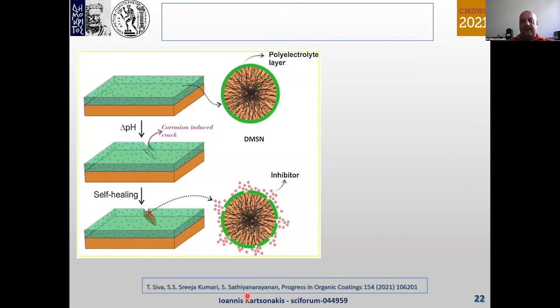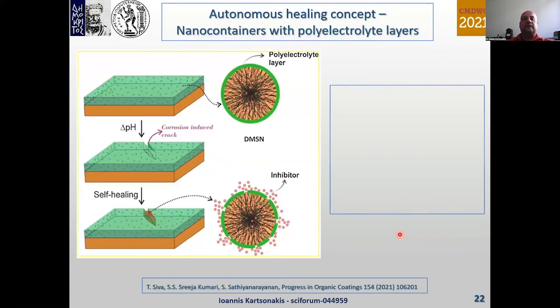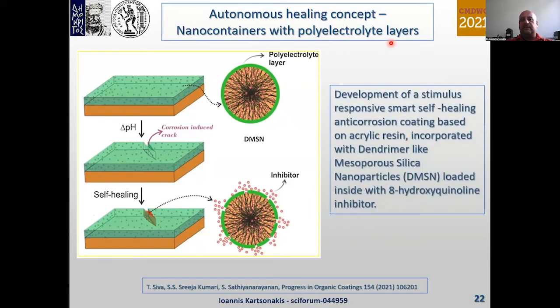In the work of Siva et al. in 2021, there was also autonomous self-healing, but this time with nanocontainers with polyelectrolyte layers. There was a development of stimuli-responsive smart self-healing anti-corrosion coatings based on an acrylic resin that had inside dendrimer-like mesoporous silica nanoparticles. These nanoparticles were loaded with the corrosion inhibitor 8-hydroxyquinoline, and on the surface of the nanoparticles, there was built a polyelectrolyte layer that was pH sensitive. So after pH variation, the polyelectrolyte layer opened and there was a release of the inhibitor.